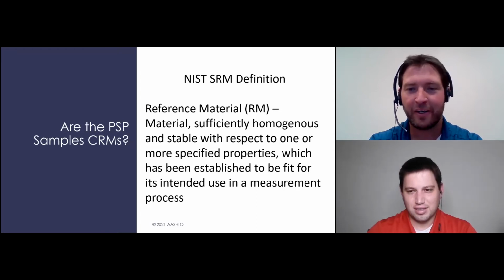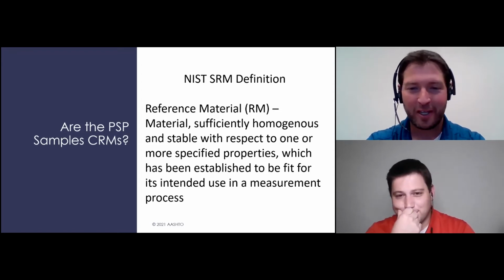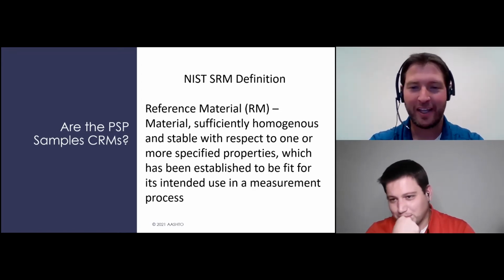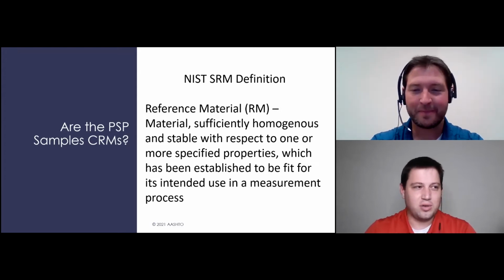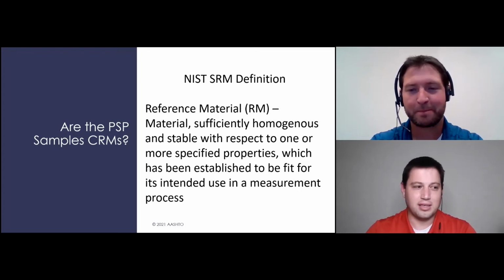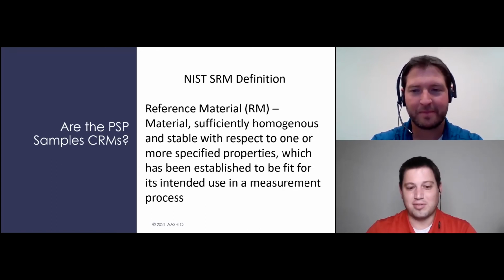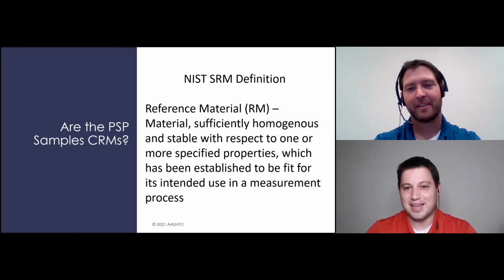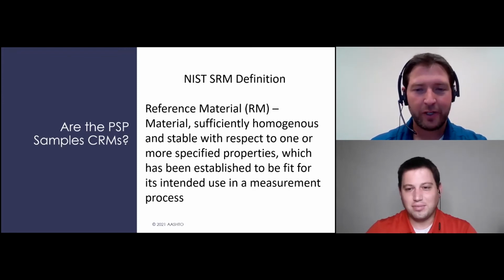But when you look at the variation, the percent passing, what, Ryan, we've seen some less than 3/4% passing the 200. I mean, even a 1/10%, and it fails a t-test from the round, and you sit there and scratch your head and say, I don't know what we're going to do to ever get this to work. Right. We have some that are so homogeneous that it'll fail stability, where the testing will be within 2 to 3 thousandths on the results, and that's too homogeneous for our stability statistics to pass. Yeah, it kind of puts us in a little bit of a catch-22, but we are looking into that.